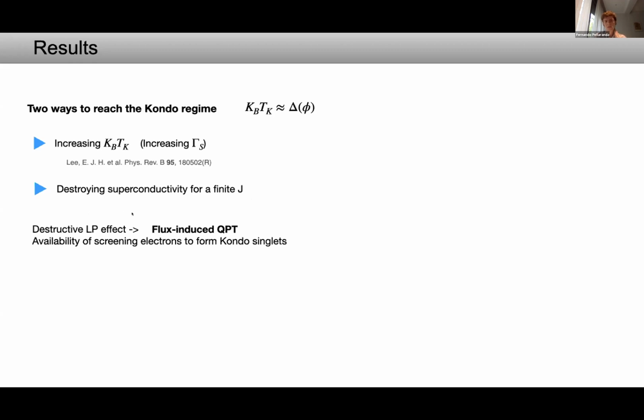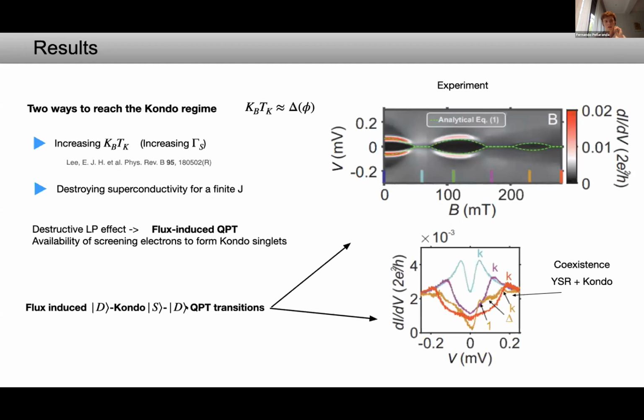So the destructive Little-Parks effect induces flux-induced quantum phase transitions, since it determines the availability of the screening electrons to form Kondo singlets. If we look at this experimental data, here we can start at a doublet phase, go to a Kondo singlet, and go back to a doublet ground state as we cross a flux region with full suppression of superconductivity. So the line cuts previously shown by Jukos clearly indicate this formation of Kondo singlets.